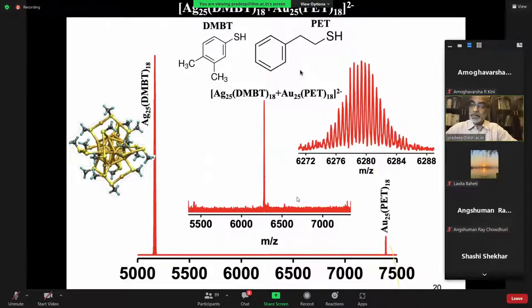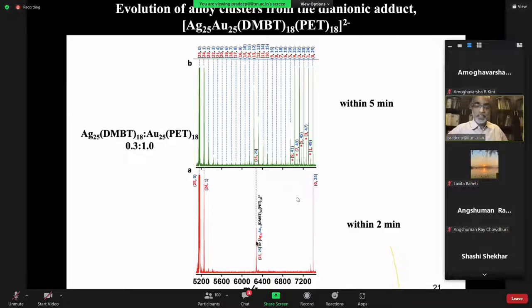Now, if at all these cluster reactions happen, this cluster A and this cluster B should come together and form an AB. Do you have this AB? Well, just after 2 minutes of mixing, this is what you see, and this is in fact an AB 2-, and you see the corresponding mass separation in the mass spectrum. So therefore, we thought that this is what the peak is, and many other peaks are forming just from this.